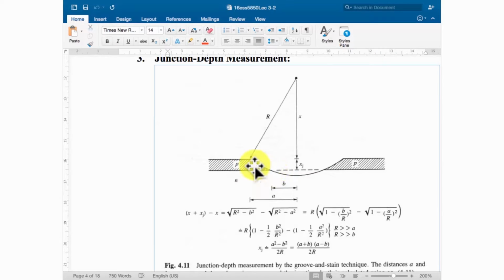The length expands the thickness, and you can visualize this length under the microscope. From the length, you can use the equation down here to calculate the thickness. Because there is a slope here, the length will be much larger than your thickness. For example, you have a thickness around 500 nanometers, but the length can be a couple of microns. A couple of microns is easier to measure under a microscope, so the measurement will be more accurate than directly measuring the thickness of the diffusion layer.